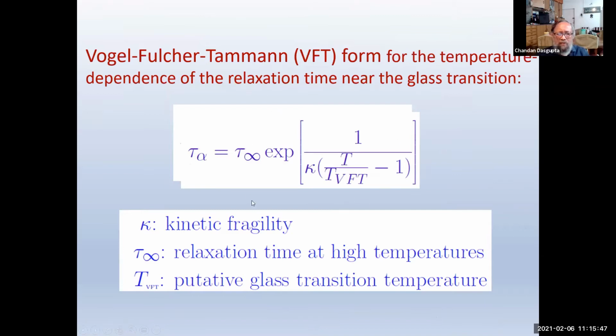So this form is pretty simple. T is the temperature, and this is the variable that we are looking at, viscosity or relaxation time. And as you can see here, there is a special temperature, which I'll call T_VFT, at which this relaxation time is supposed to diverge. So that is the ideal glass transition, and one is interested in what causes that kind of a transition and why this particular form of the dependence of the relaxation time on temperature provides a good description of the behavior of fragile liquids.